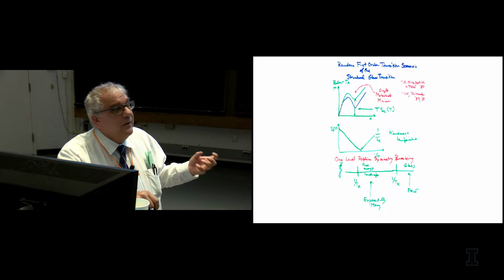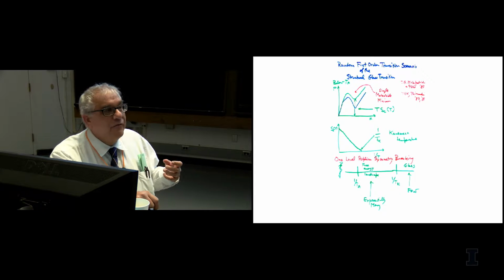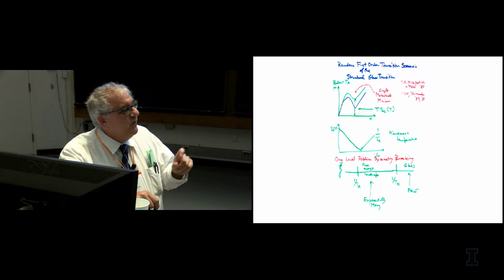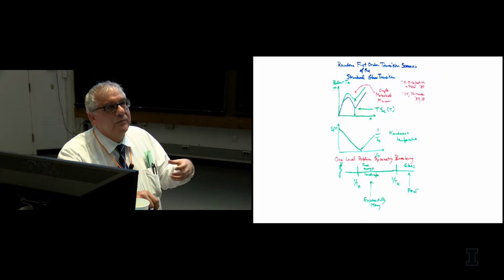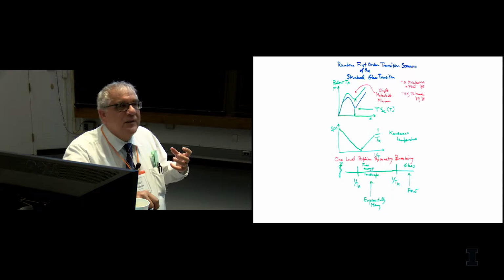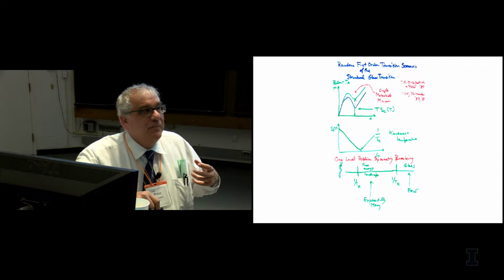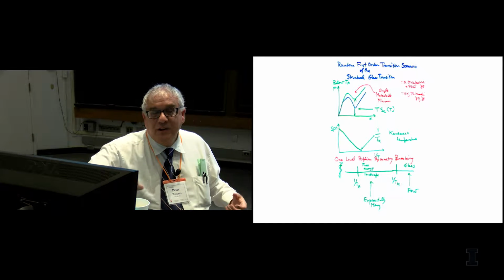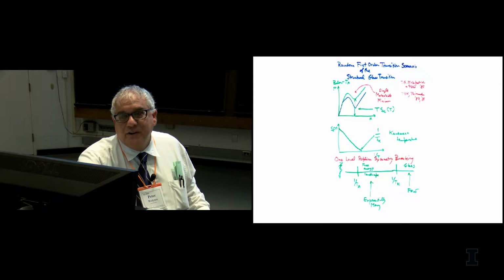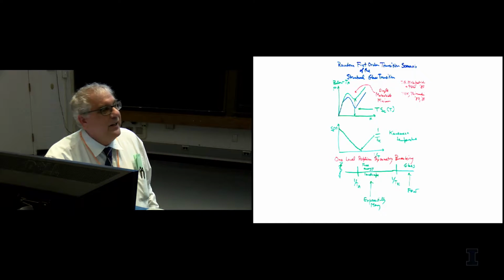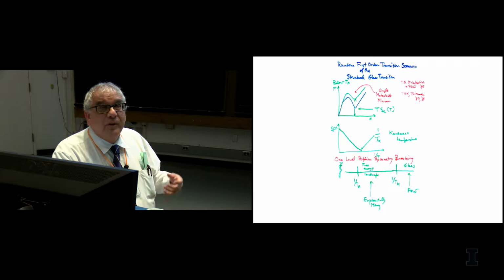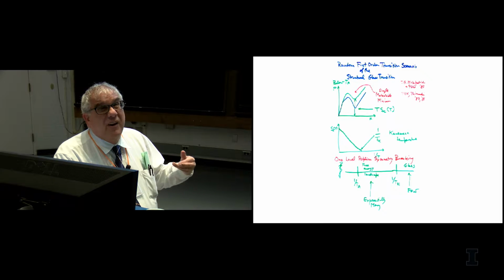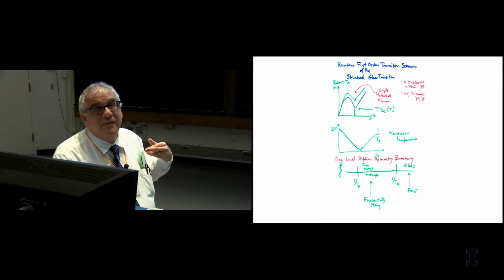And this caging means that there's a free energy minimum in which you vibrate only, say, a tenth of a particle spacing before you run into another cage. This is very much like the Lindemann criterion in melting. There's a certain temperature at which there would be a Lindemann criterion for being caught in a cage. This temperature is called TA. At this temperature, fluids are really not all that viscous by our standards.